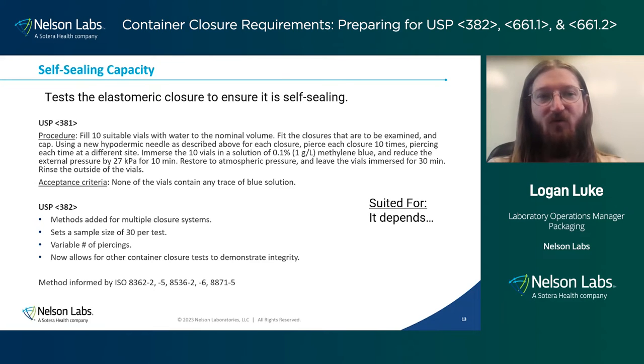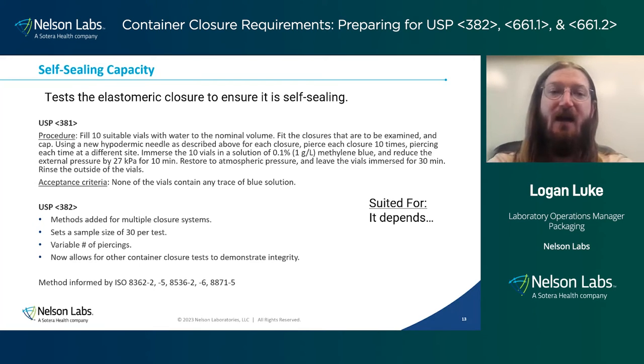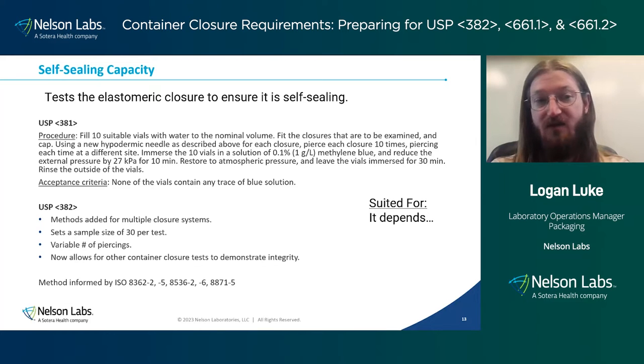The final test that was shared with USP 381 is the self-sealing capacity test. And it used to be pretty easy, where you take your vial, you puncture it 10 times, and then you do this dye immersion test with the methylene blue dye to check for blue dye in the water inside. So now there are multiple methods for the multiple closures, and they have prescribed a sample size of 30 rather than 10. The piercings that you do are meant to mimic the intended use, right? And this should mimic the most challenging intended use that you have.